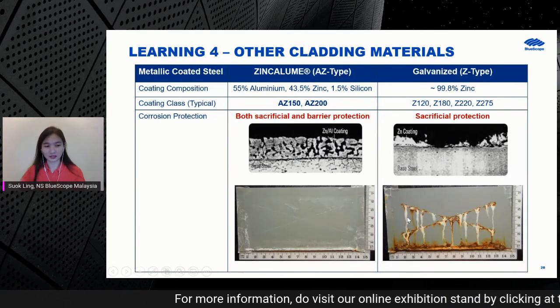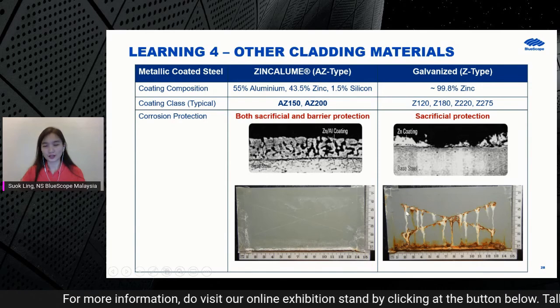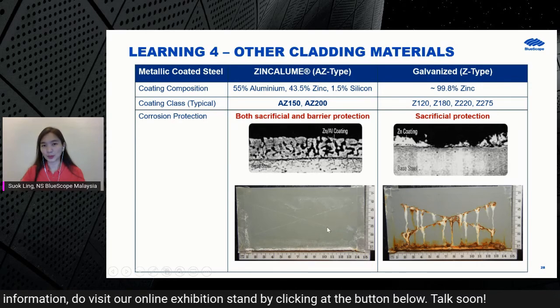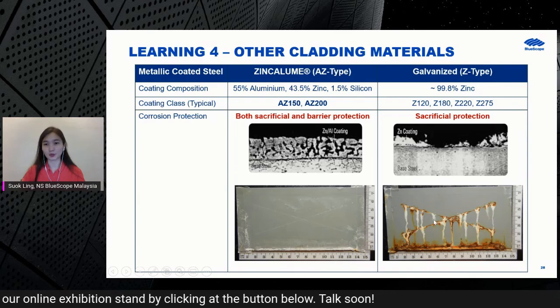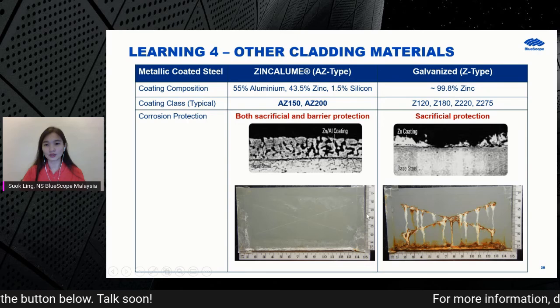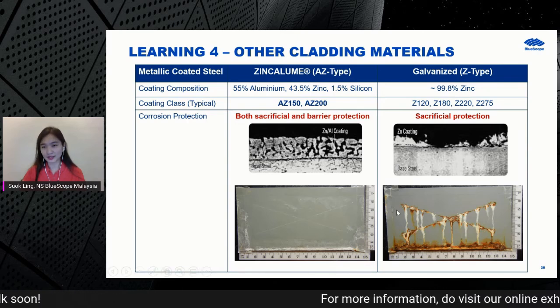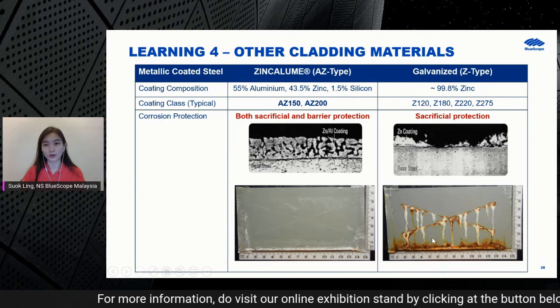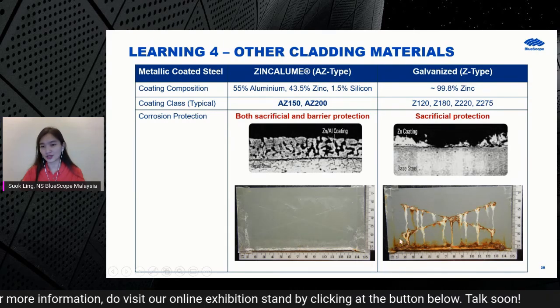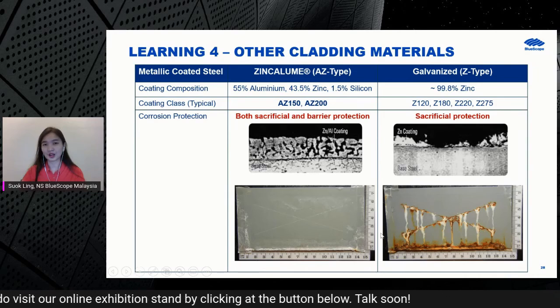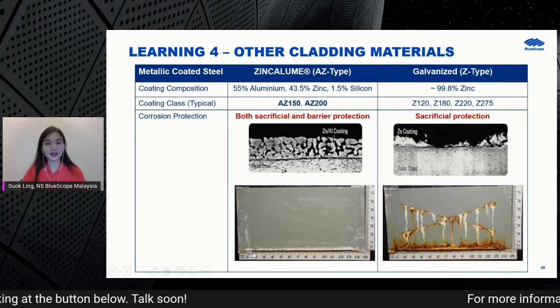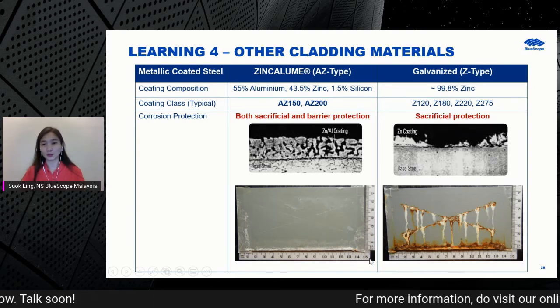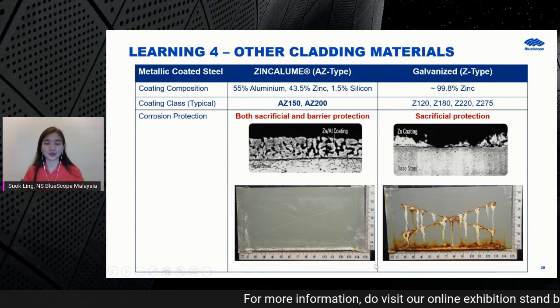And these are the accelerated corrosion tests. We are using the pre-painted AZ type versus the pre-painted Z type over here for a cyclic corrosion test after 2,000 hours. So for pre-painted Z type, we tend to see there is a sign of red rusting corrosion for all the opening areas, such as the cut edges and also the scribe line. However, for the pre-painted AZ type, we do notice there is a sign of reactions happening over the cut edges, but we haven't seen any red rusting corrosion yet.